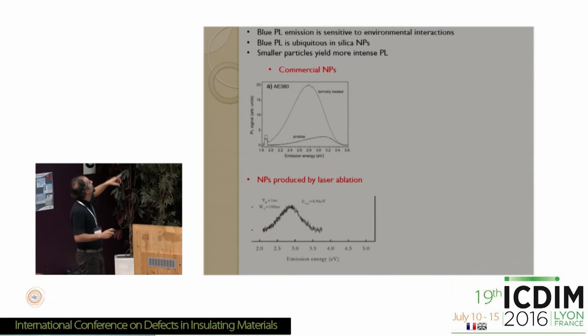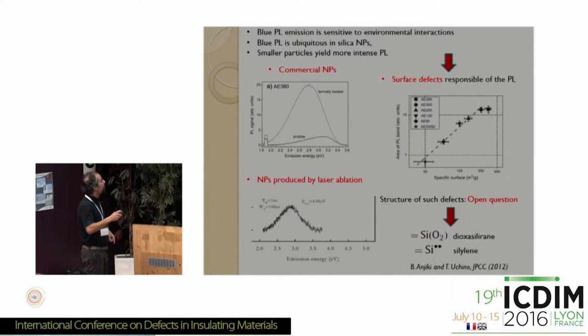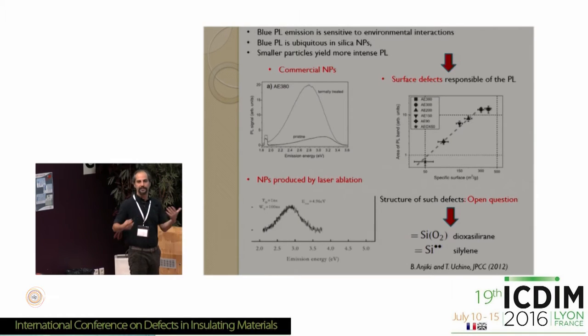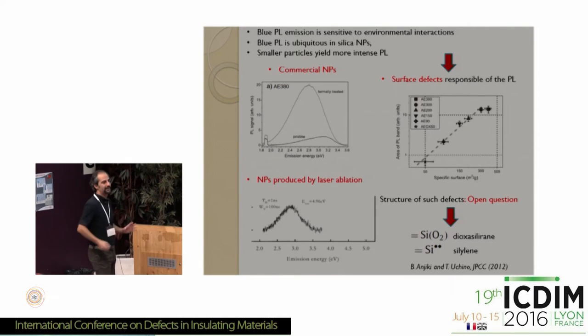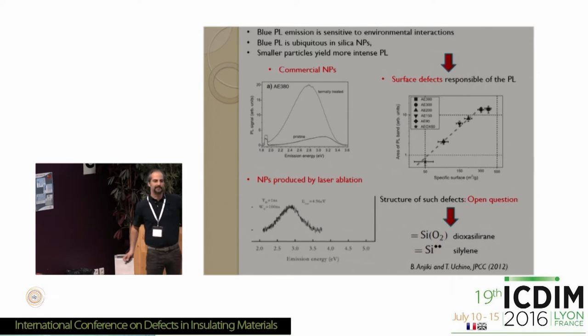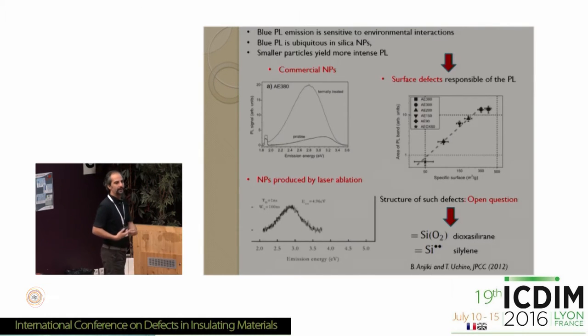However, this tends to grow with the inverse of the size of the nanoparticles. Here you can see the area of this emission as a function of the specific surface of the nanoparticles. So the smaller the nanoparticles are, the larger their specific surface, the more intense the luminescence is. Okay? And also this emission is quite sensitive to environmental interaction, meaning that, for instance, in solution, it's sensitive to pH, or it's sensitive to the atmosphere where the nanoparticles are in, and so on. So these results, together with the environmental interactions, make people think that the blue PL comes from surface states, as I anticipated during the introduction.